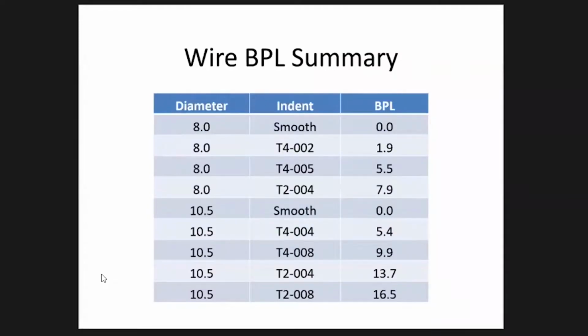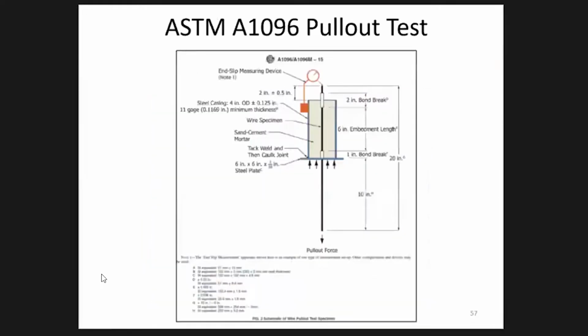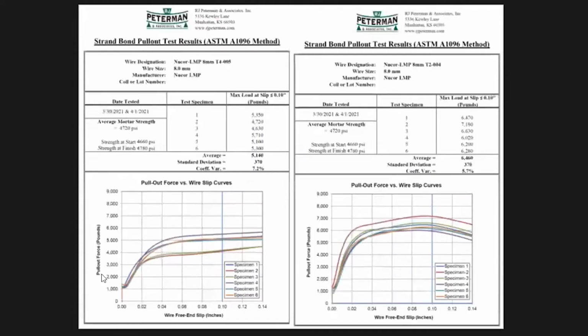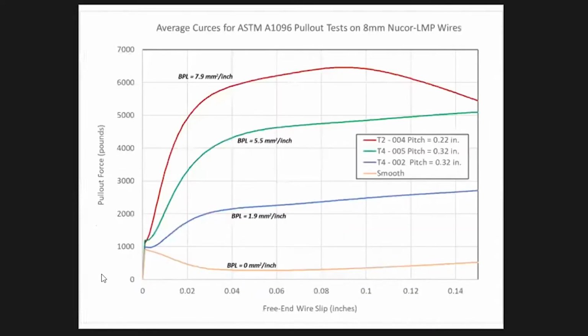So the bite per length varied from 0 all the way up to 16.5 mm2/inch. We have a large variation in bite per length. And we did ASTM pullout tests with each one. The pullout test is actually an average of 6 individual tests. The way the ASTM has you report it is you do 6 tests and you report the value that is the maximum force at an end slip less than or equal to 1/10 of an inch. Well, if I average those curves, just take the average of those 6, these are the results for the 8mm wires. And this is the average pullout curve, and I'm putting the bite per length on each wire.